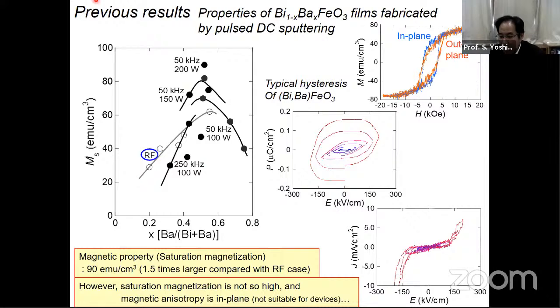This is the previous result. In the case of the bismuth barium FeO3 film, this graph shows the saturation magnetization of this material. The highest magnetization value is around 90 emu per cc. This value is 1.5 times larger than with the normal RF sputtering system. This indicates film quality is very high compared with the normal RF sputtering system.